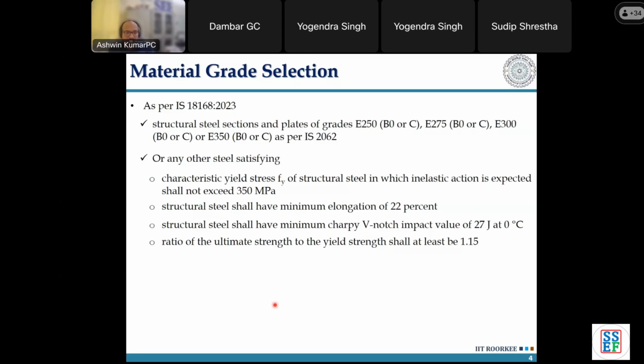The second requirement that the steel should have is a minimum Charpy V notch impact value of 27 joules at 0 degrees Celsius. Now, I'll make you understand this. And the third criterion is that the ratio of ultimate strength to yield strength of the steel should be minimum 1.15. Now, you have to understand that all these three clauses that I've mentioned directly from the code, which relate to percentage elongation, the Charpy V notch test requirement, as well as the ratio of Fu by Fy, were earlier there in IS 13920. If you check for RCC, for reinforcement bar, this clause was earlier there, but it has also been introduced in this particular code as well.